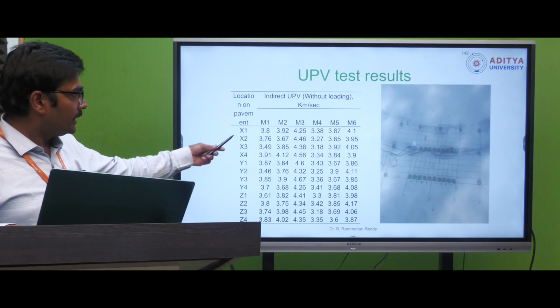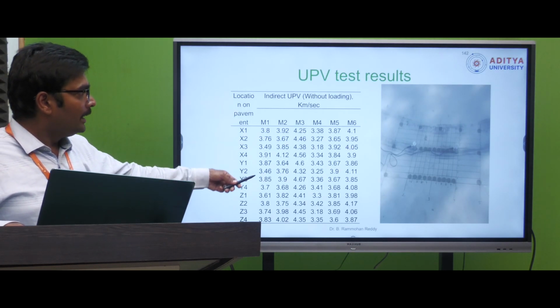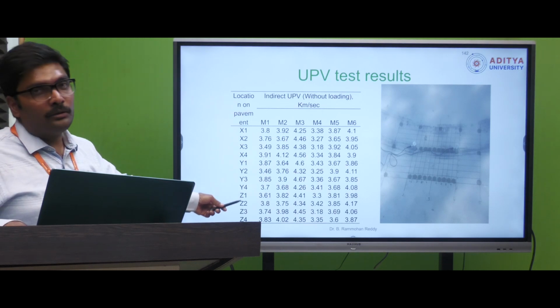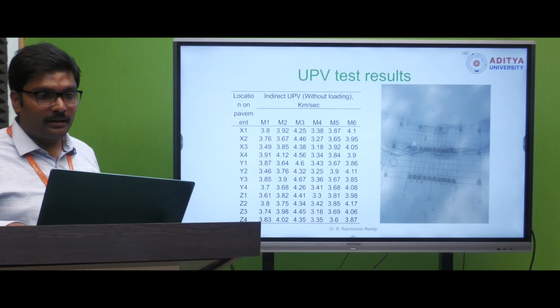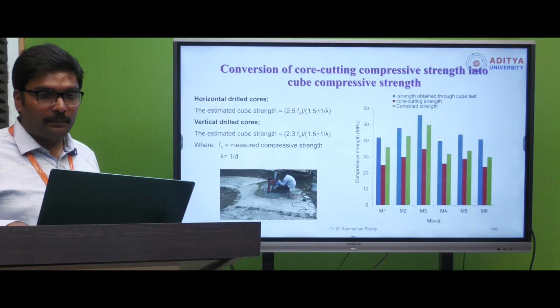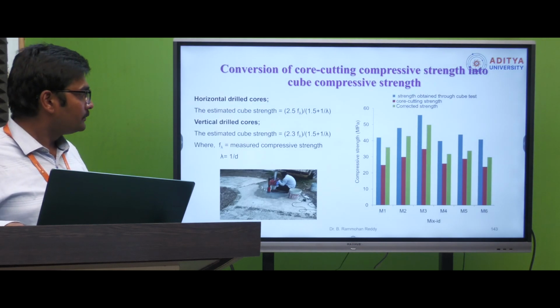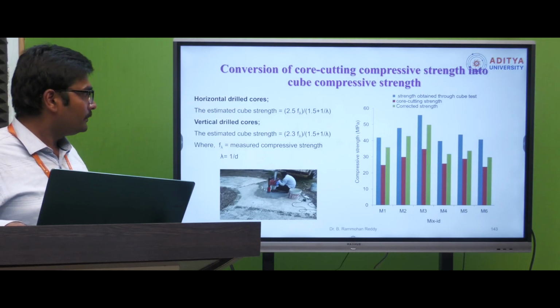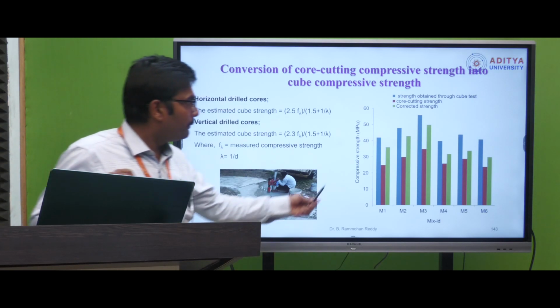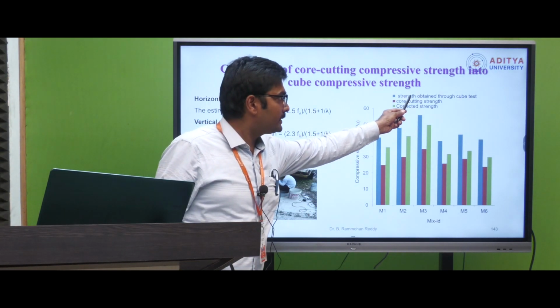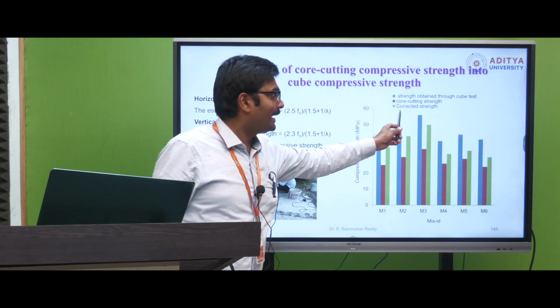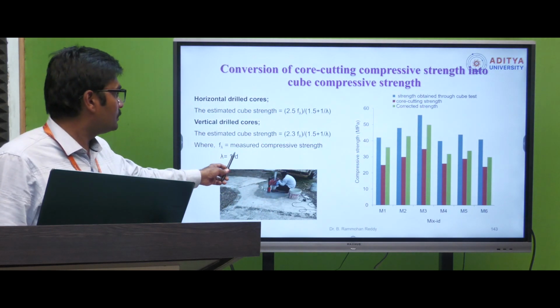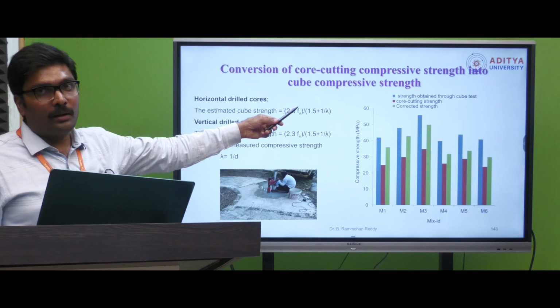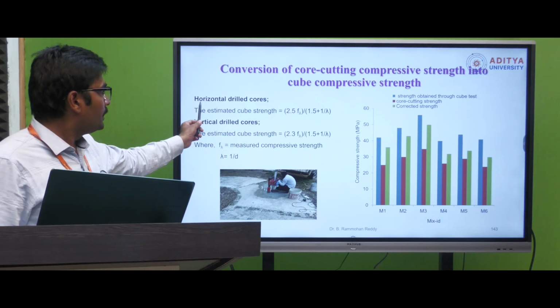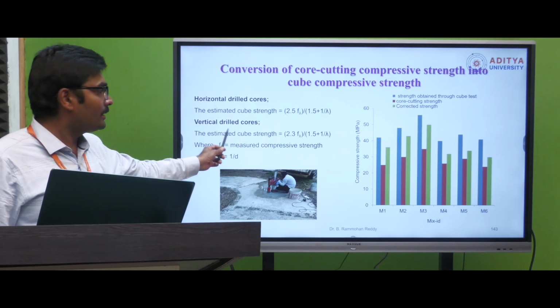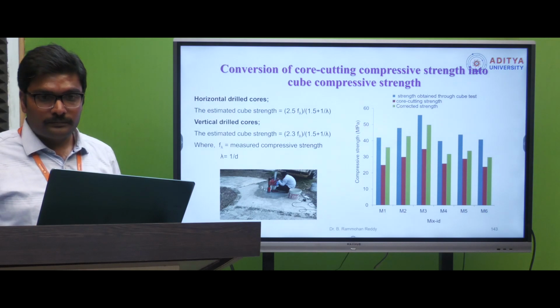And ultrasonic pulse velocity we have done, and it indicates the strong matrix which we have observed in all the geopolymer samples. Core samples were collected to find the compressive strength, and we compared the strength obtained through cube test and also core sample strength and corrected strength. These are the equations which we will use to correct the core sample strength to the compressive strength of the cube, either it may be horizontal drilling cores or vertical drilling cores.